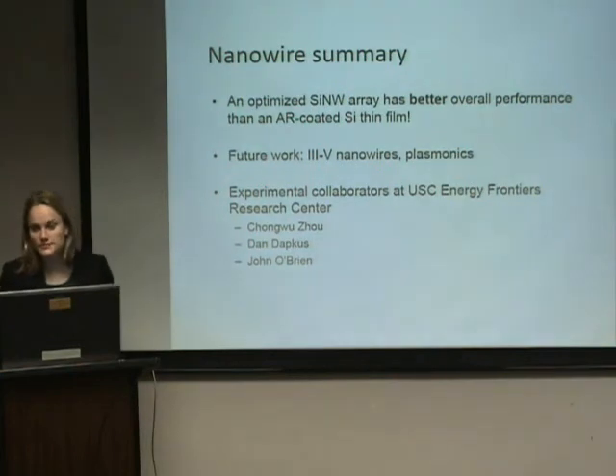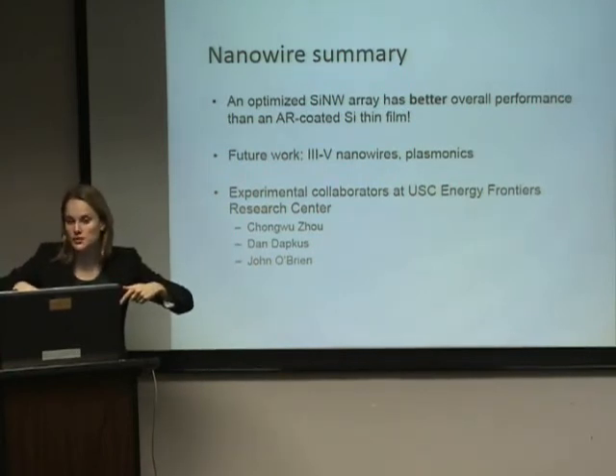You're trapping, right? Yeah, there's a trapping effect in the layer. I'm trying to understand how this thing works. Right, so if you just had a semi-infinite layer, very thick, then you just absorb as you go along, and it depends on the absorption length, and that varies with frequency.